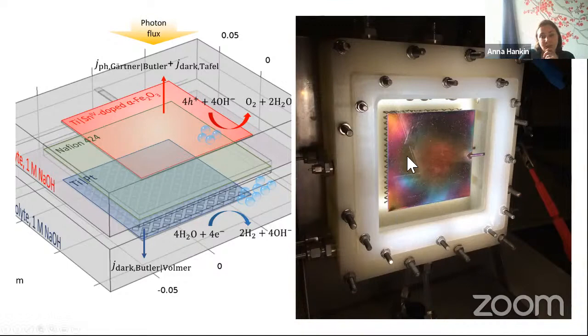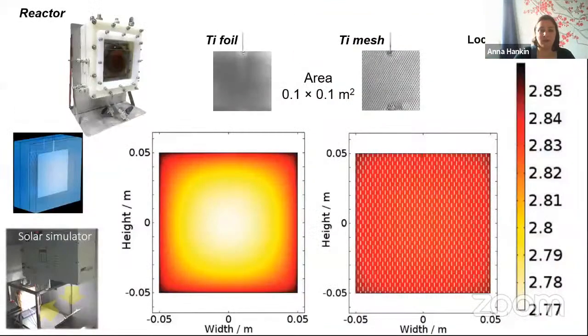So here in the picture, you can see hematite deposited onto a titanium plate. And then it's got a titanium rod welded to it, which is then taken out of the reactor, and the electronic contact is made externally. And we compared the performance of hematite on a solid titanium foil with the performance of hematite on a titanium mesh. And the idea is that if you have a mesh, it introduces the ionic shortcuts to homogenize the electric field distribution between the suboptimally oriented photoanode and the cathode behind it.